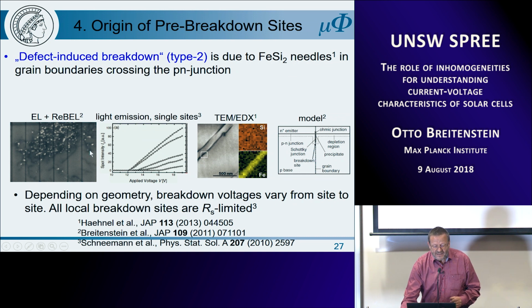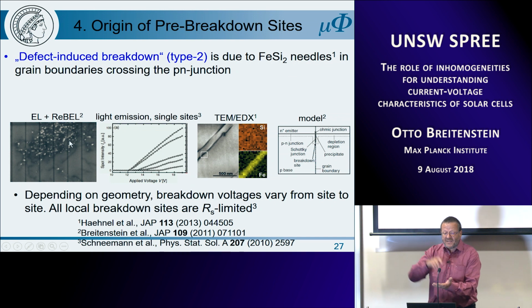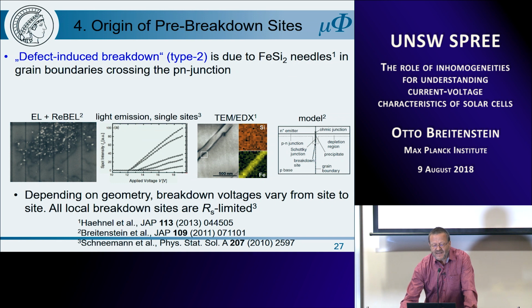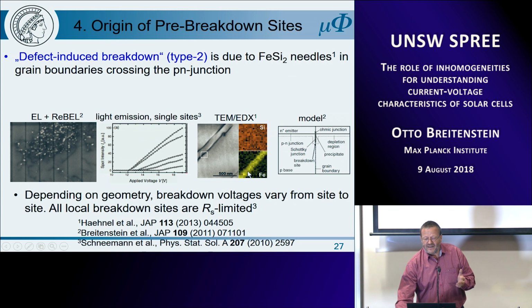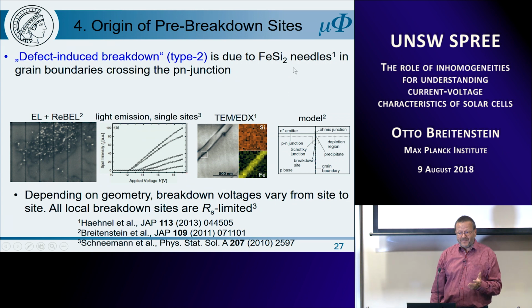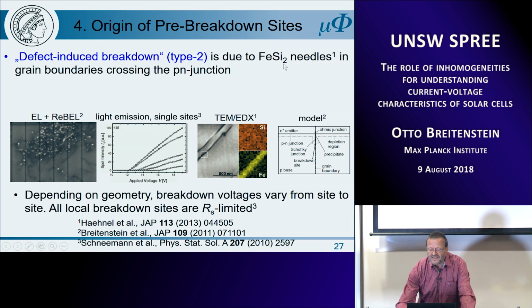And Schneemann and co-workers at the Forschungszentrum Jülich have found that by locally detecting this luminescence, different breakdown sites have different breakdown voltages, and also their slope can be different. And we have performed in these positions TEM, transmission electron microscopy, and EDX, and have seen that in the position of these breakdown sites we have iron silicide. Actually, it is iron disilicide, and it's quasi-metallic.